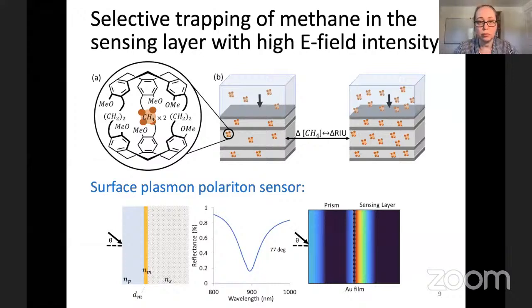The only sensor that fits this description of simplicity and accuracy is a surface plasmon polariton sensor. It's a pretty simple configuration where there is a prism on which we have a thin metal layer, which supports the surface plasmon resonance. On the other side, there is a sensitive polymer matrix that selectively captures methane. It changes the refractive index of this polymer very, very slightly, but enough to detect spectral or angular changes in this resonance that originates because of the excitation of the surface plasmon mode on the metal-dielectric interface.